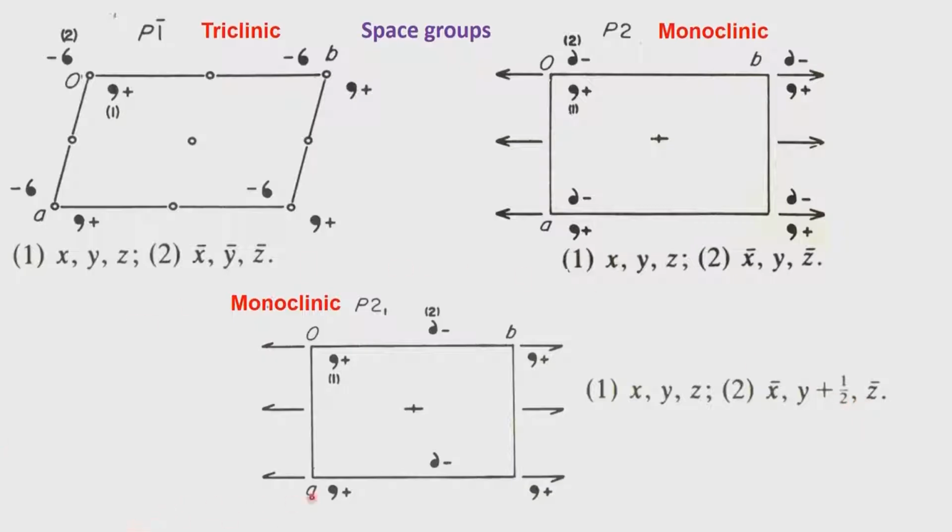Notice that we can also have the two-fold screw axis symmetry at 0 as well as 1. The presence of the translational periodicity has brought us the additional 2-1 screw axis, just like the logic we use for P2 and also for the triclinic system. So, these are the three simplest of the space groups we can discuss with respect to the equivalent points, with respect to special positions, and with respect to the generation of the equivalent points, and Z is equal to 2, and if there is an object which has a two-fold symmetry, then Z will be equal to 1.